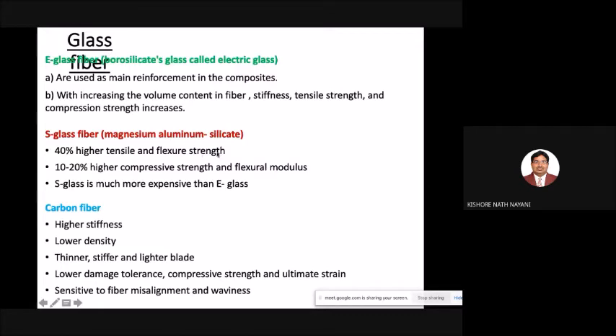40% higher tensile and flexural strength, 10 to 20% higher compressive strength and flexural modulus. S-glass is much more expensive than E-glass. Then carbon fiber is very costly and generally not used, but in some specific applications where you want lightweight, you can use carbon fiber. Then high stiffness and low density: thinner, stiffer and lighter blades can be made by using carbon fiber. Low damage tolerance, compressive strength and ultimate strain, sensitive to fiber misalignment and waviness.